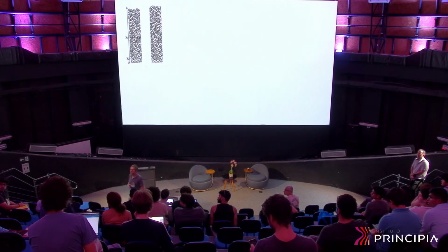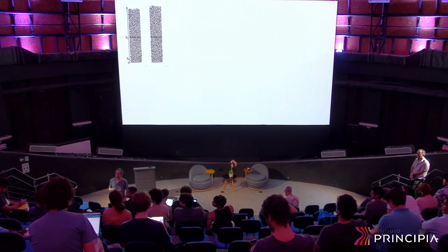Chantal. Hi, very nice talk. Thank you very much. Related to a similar question, I seem to remember that there are colloidal particles called microgels that, depending on the temperature, can swell or shrink. People such as Dave Weitz studied the behavior of very dense suspensions of microgels, and depending on the temperature, this system can change from a fragile to a strong glass. It is true that it's not the same, but these particles can swell with temperature. So maybe an experiment with a temperature gradient could be used to...